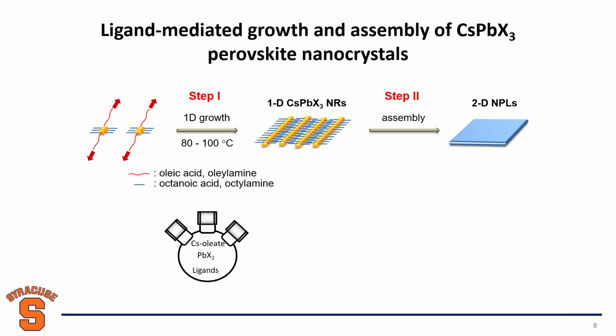Later, when we form one-dimensional nanorods, we can use these to form 2D nanoplates by material assembly. We think it's a ligand-mediated behavior because with high packing density on the side walls, you can have non-polar interactions, van der Waals interactions, right? But we know van der Waals interaction is not a primary bond, it is very weak, so we wanted to give them a little bit of help. So what we did is we put them in an autoclave. We apply pressure. We force them to fuse together to form 2D materials.